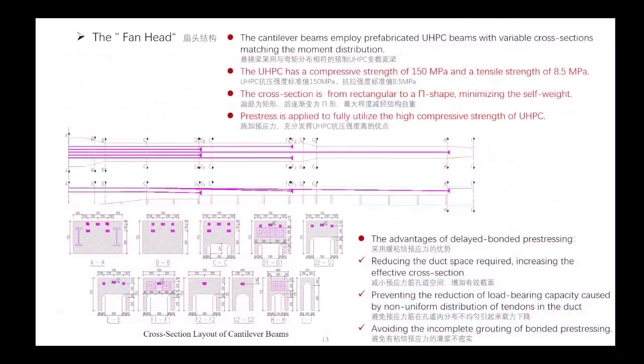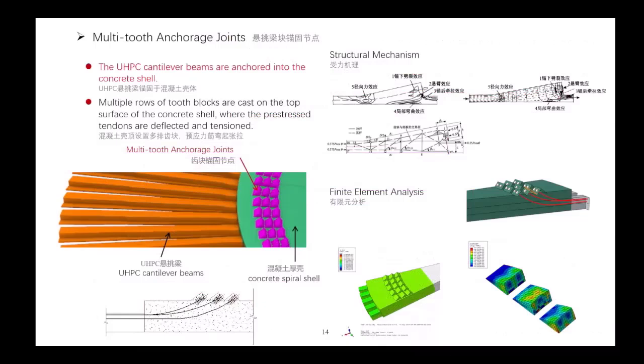The compressive strength of UHPC is 150 megapascals, and the tensile strength is 8.5 megapascals. The cross section is formed from rectangular to a Pi-shape, minimizing the self-weight. Prestress is applied to fully utilize the high compressive strength of UHPC. The UHPC cantilever beams are anchored into the concrete shell.